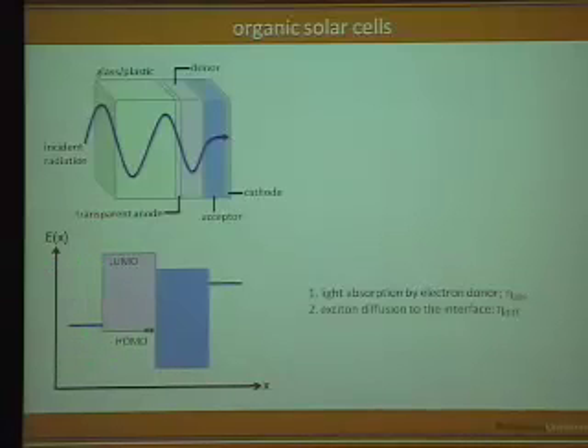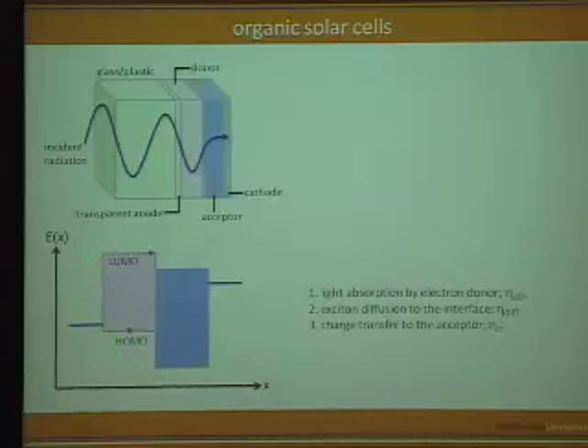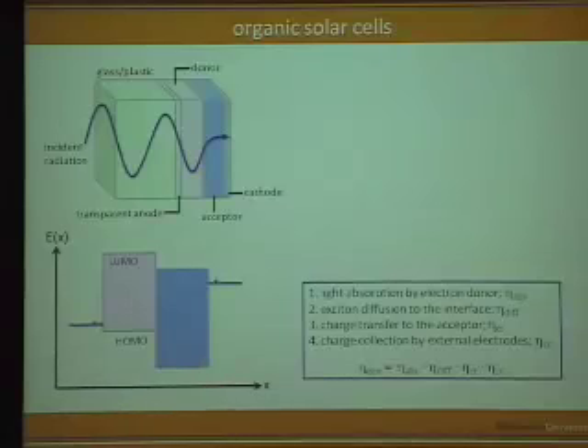And so when you shine light, light gets absorbed in the donor, and then you generate an exciton. This is a tightly bound electron and hole pair. The electron then shifts to the LUMO level, and the hole remains in the HOMO level, and these get collected at the external electrodes. So solar cells are inherently not very efficient devices. Organic solar cells especially are not very efficient. The highest efficiency that's been reported a couple years ago is about 6%.